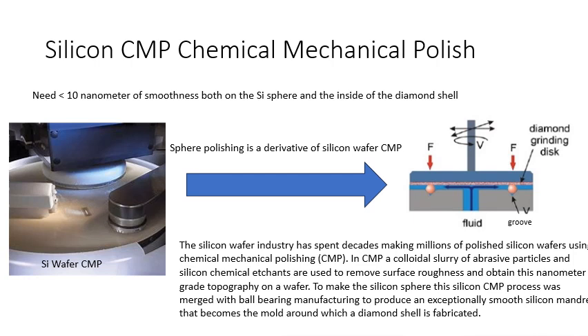One of the steps that are used in polishing wafers is called chemical mechanical polishing. You're getting nanometer surface smoothness, polishing this better than most mirrors would ever be polished. You use a combination of what's called a slurry. So it's a fine grit coupled with some reactive chemicals that actually etch the silicon surface. So you're polishing it flat. That's how you make a silicon wafer.